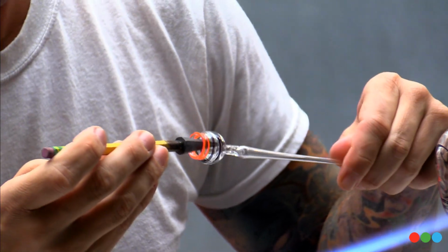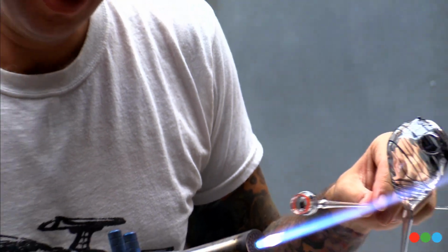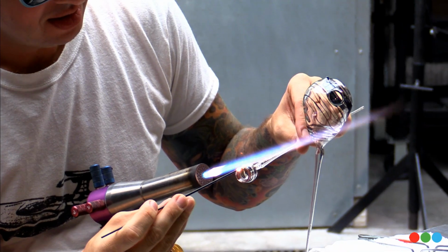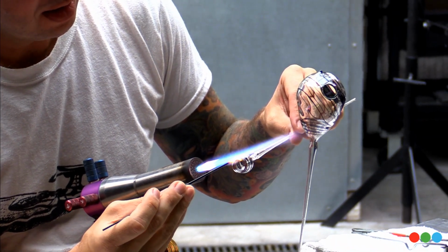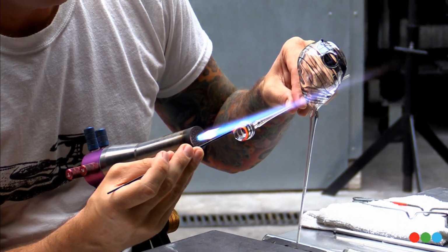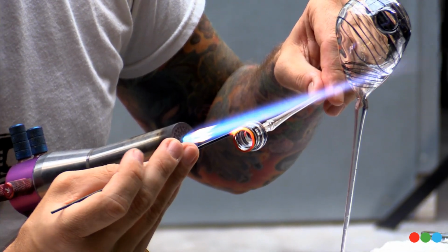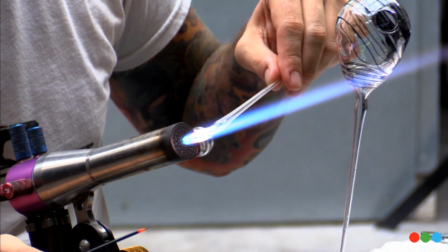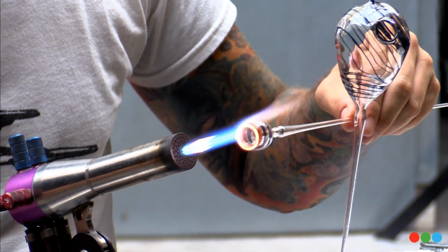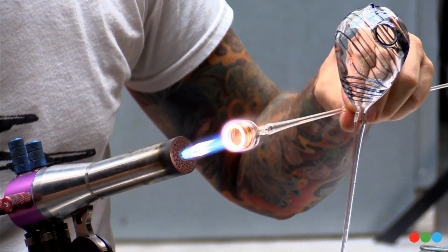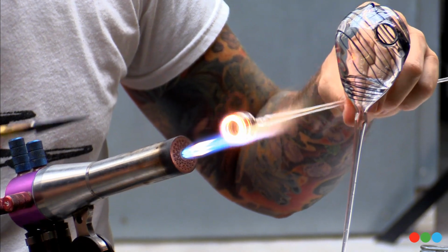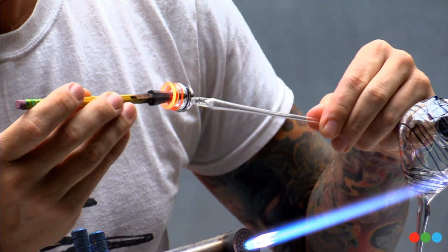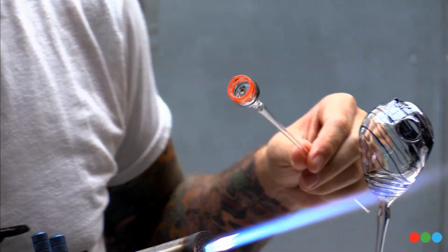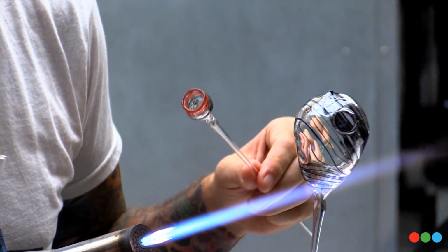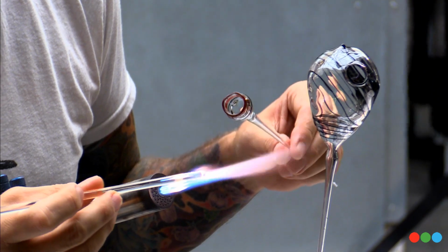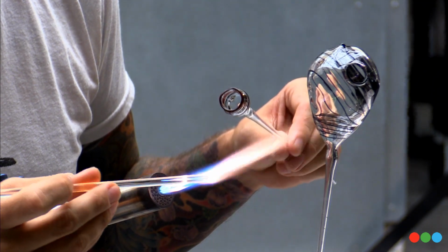This type of glass, being more thermally shock resistant, he can actually allow this thing to cool all the way down to room temperature, and it probably won't crack as long as it's been constructed well. But there's still stress inside the glass, and it could crack at any moment. So even these objects need to go through that slow cooling process. So at a later date, and really the sooner the better, as soon as he finishes making it, we'll put it into a kiln, heat it up to 1,500 degrees, that's the annealing point of this type of glass, and then cool it slowly. Annealing is the process of relieving the stress in the glass and then cooling it slowly from there.